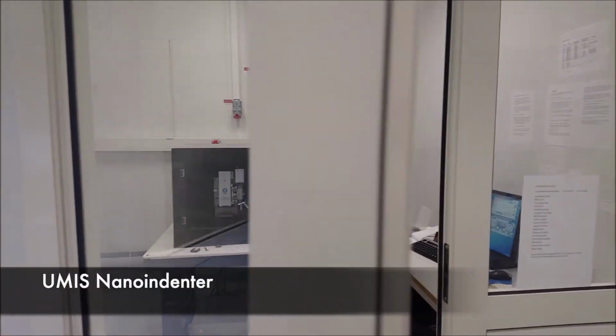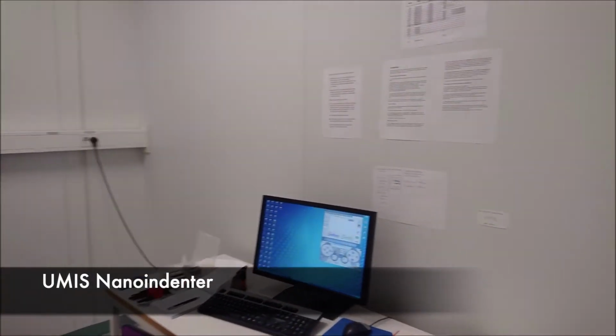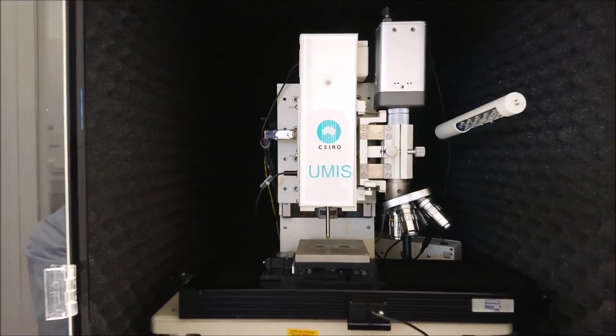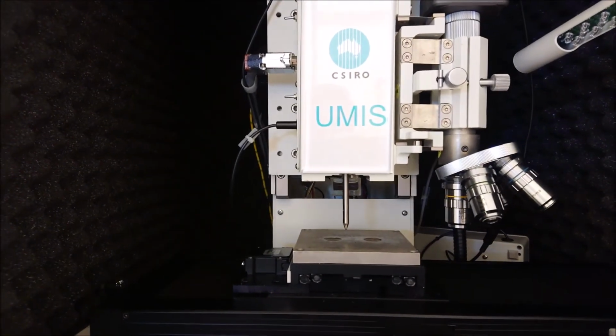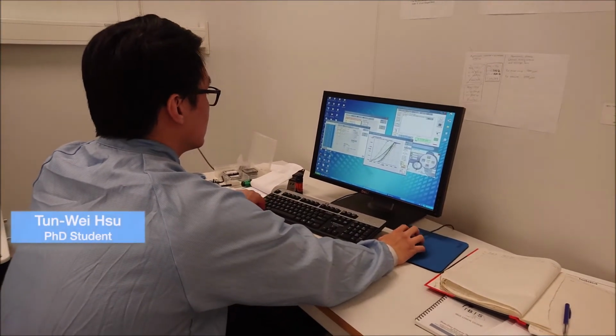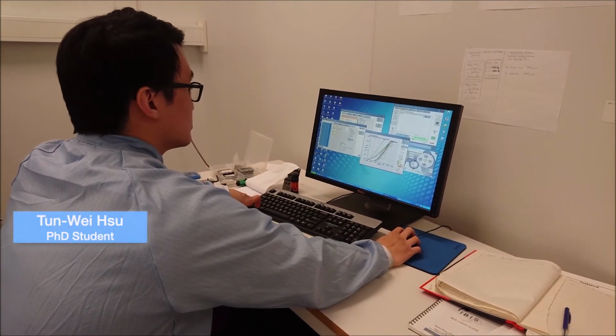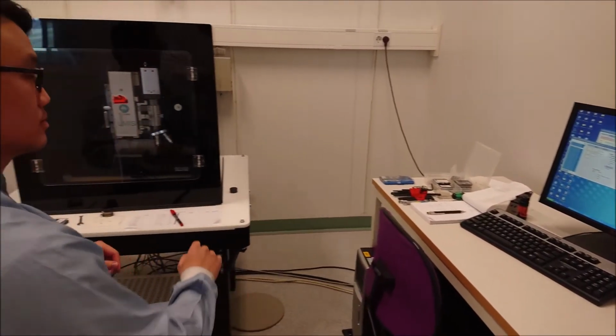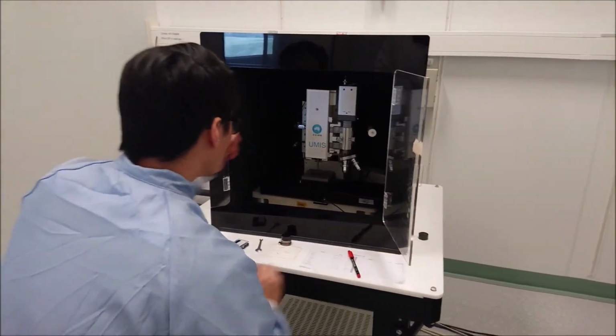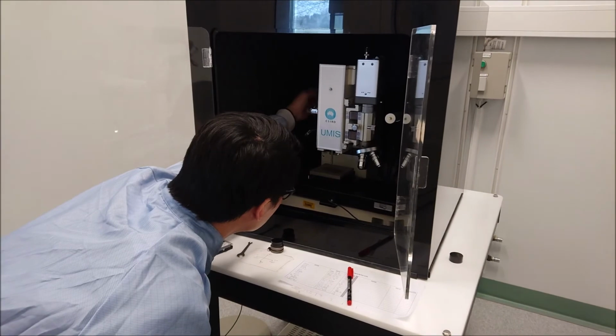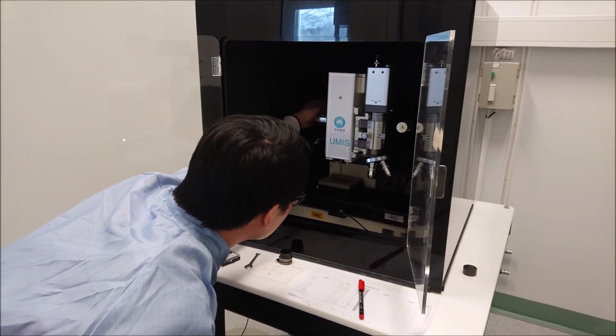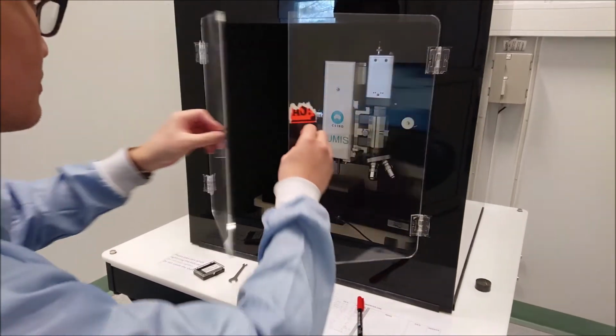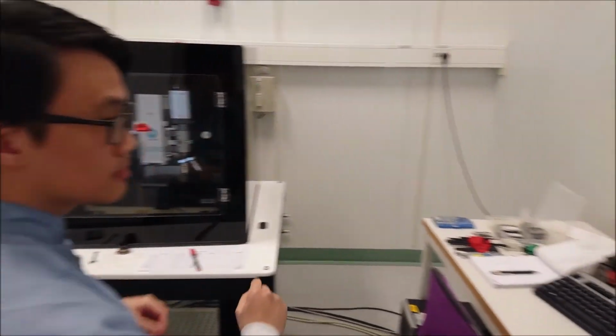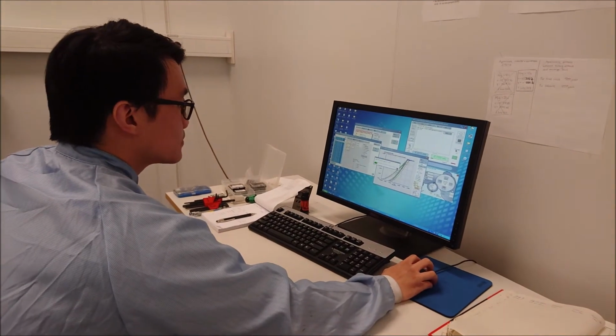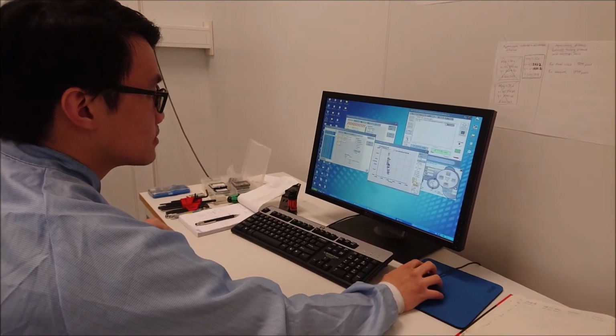Mechanical properties, for example hardness, can be measured by nanoindentation. This technique is based on the use of a diamond tip, which is indented into the sample with an increasing load to the maximum indent load, resulting in a residual area of the imprint and a load versus displacement curve during the nanoindentation measurements. The hardness can then be calculated. Hardness is one of the most frequently used properties for evaluating protective coatings. Coatings with higher hardness can have a longer lifetime and better performance during cutting applications. Other mechanical properties like elastic constants can also be calculated from software.